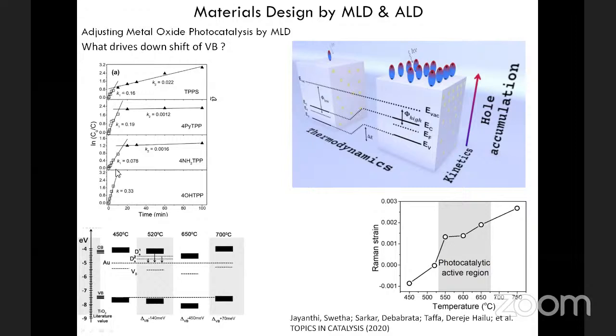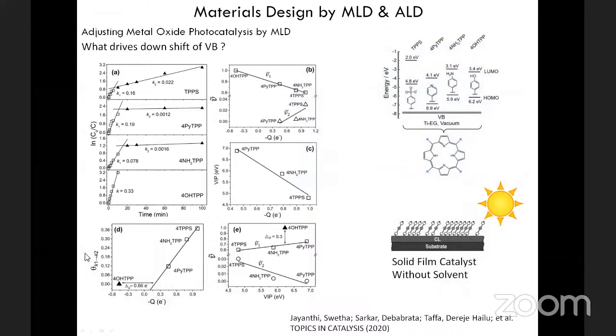The reason we have these two regimes, which is observed only for the porphyrin monolayers, is that as these photogenerated holes chew up and break up porphyrins, the dipole density goes down, and at some critical level the work function changes abruptly, and this is a well-known phenomenon of 2D dipoles on a solid surface. And this is the transition point in coverage that you can see here, which correlates very nicely with the electron density at the anchoring group. So with this, I would like to